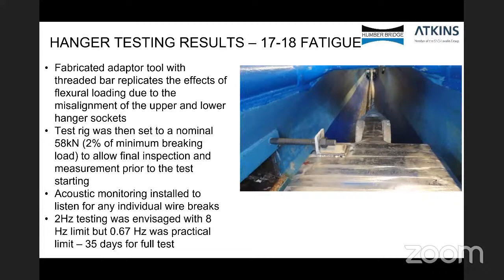This is a picture of the hanger, the fatigue testing being carried out. And the bar to the left-hand side there is actually how they induce the rotation of the socket to cause that misalignment. Now the test was then set to a nominal 58 kilonewtons, 2% of minimum breaking load, to allow for final inspections and measurements prior to the testing starting.